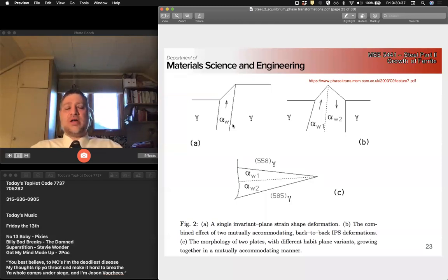So we'll talk about martensitic transformations as displacive phase transformations coming up, but there's a whole range of phase transformations that are sort of in between, where they're diffusional. They still require the carbon to partition out in the same way, but the mechanism of how the transformation happens isn't purely diffusional. The atomic planes slide past each other, and you have a corresponding transformation shear.